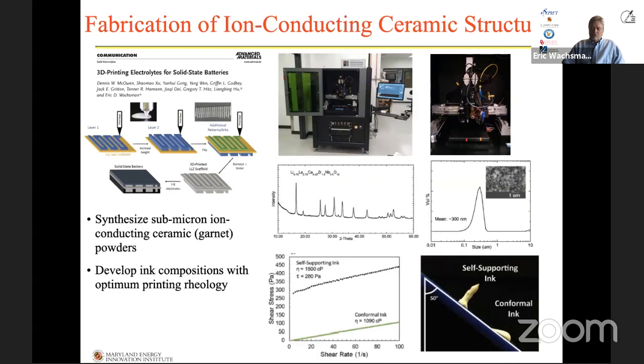The one is a self-supporting ink, which has the higher shear stress, maintains its structure, it doesn't flip over, whereas the conformal ink has too low of a shear stress and it just flows and runs down. So we want to have something that's self-supporting because we want to make these vertically aligned structures. Again, with these types of ceramics, we would then follow that by a drying and sintering step. And I'm not going to go into more detail about that, but typically they are sintered at around, as I said, 1,000 to 1,100 degrees centigrade.